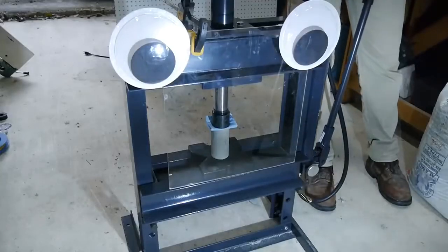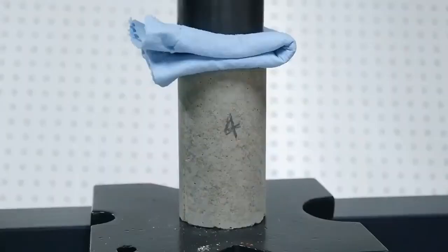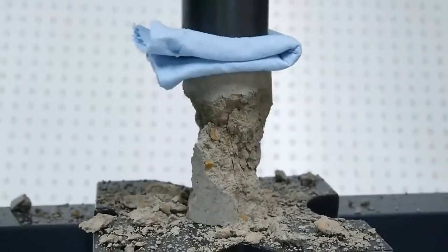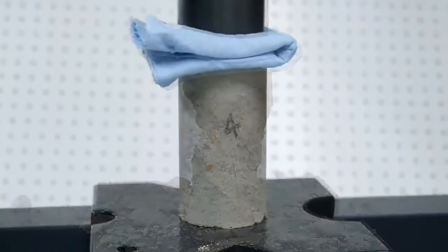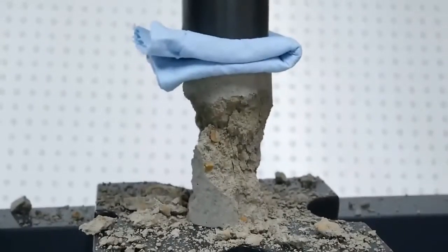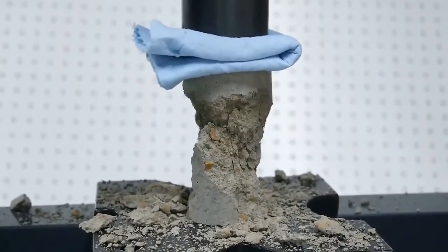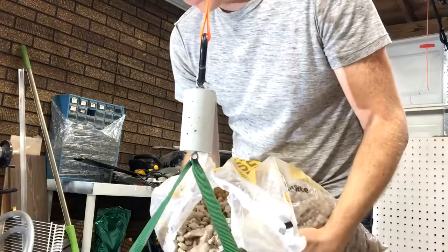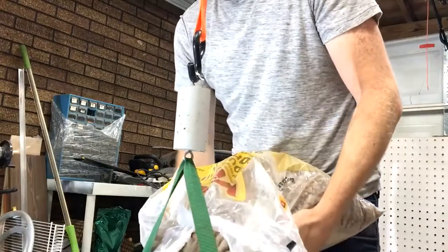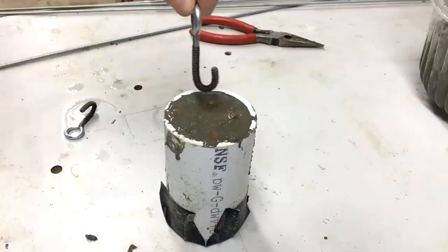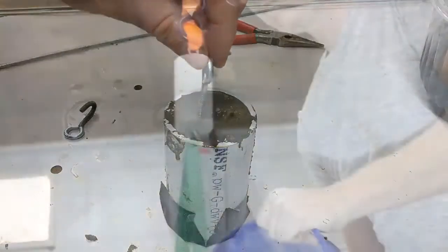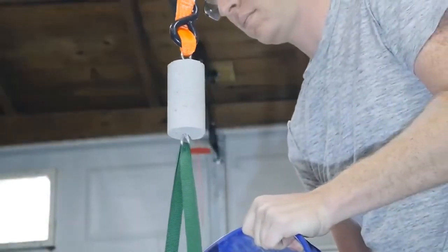First, the compressive test. Under compression, the cylinder broke at a load of about 1,000 pounds. That's 450 kilos. For concrete, that's pretty low because I included a lot of water in this mix. The reason is my rig to test tensile strength isn't quite as sophisticated. I cast some eye bolts into the sample and now I'm hanging it from the rafters in the shop.